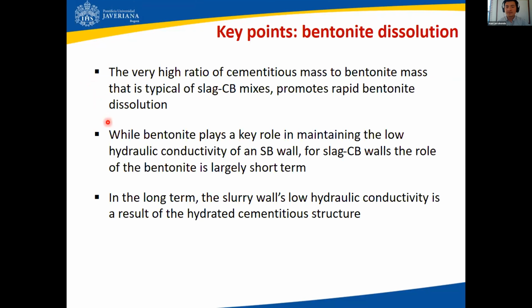Second, while bentonite plays a key role in maintaining the low hydraulic conductivity in a soil bentonite wall, like I said, that's the main practice in the US, for example. In slag-CB walls, or even CB walls probably, the role of bentonite is largely short-term. You can see that within the matter of days, the bentonite structure basically fades away.